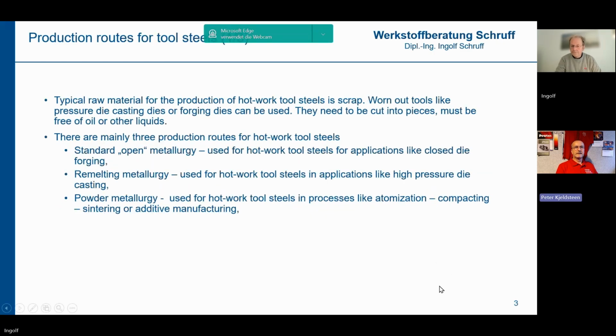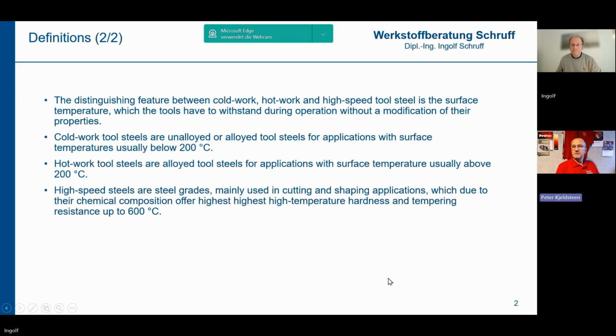So if we dig deeper into how these steels are manufactured, I remember when I was working with tool steel, many of the alloys were just melted and cast into a steel mold. But some of them were remelted to remove the slag, the electro slag remelting process. I think it was only for hot work steel they were remelted, never for cold work, as I remember it.